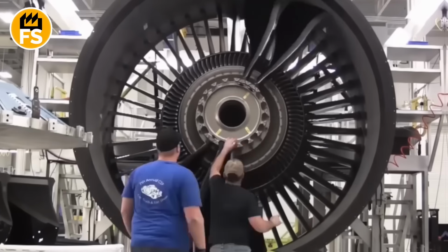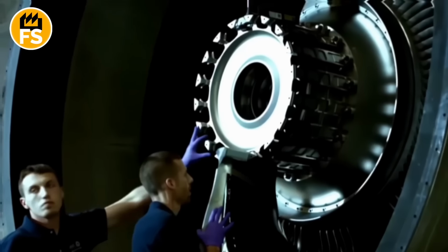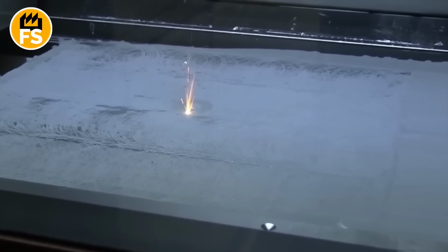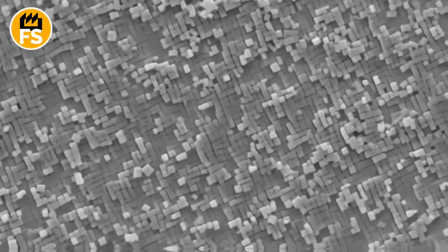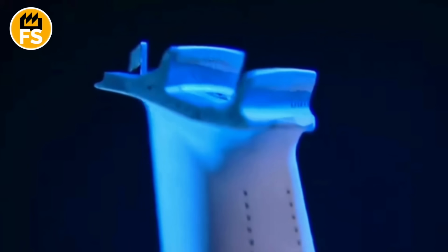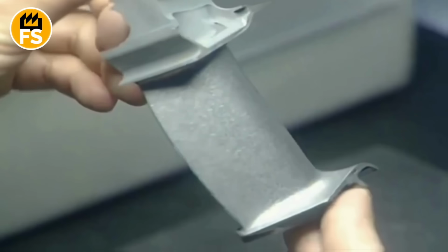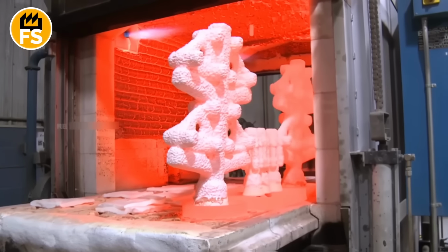Single crystal blade technology lets manufacturers use rhenium more efficiently. Instead of a polycrystalline structure, the blade is grown as one massive crystal with no grain boundaries, the weak spots. This allows them to reduce rhenium content while maintaining performance. But the process is complex and expensive. Each blade is grown individually in specialized furnaces with extremely slow, controlled cooling.